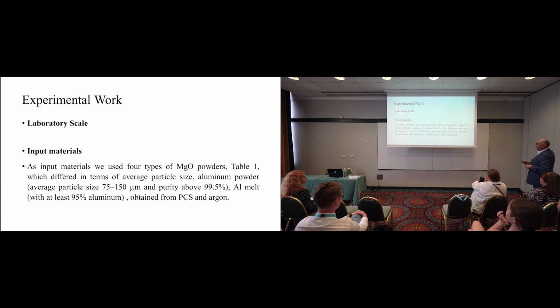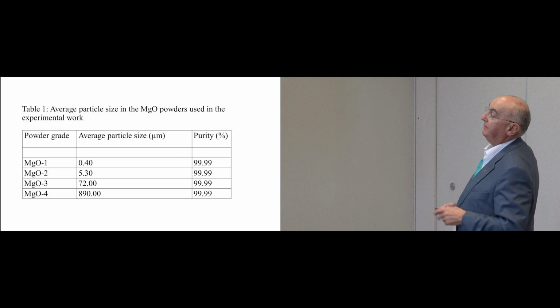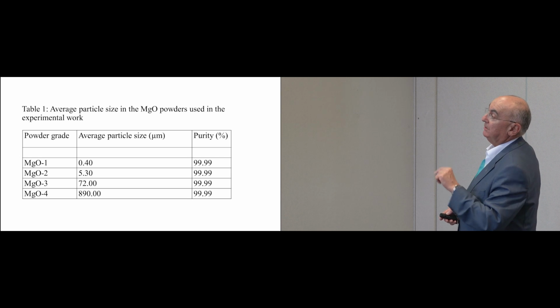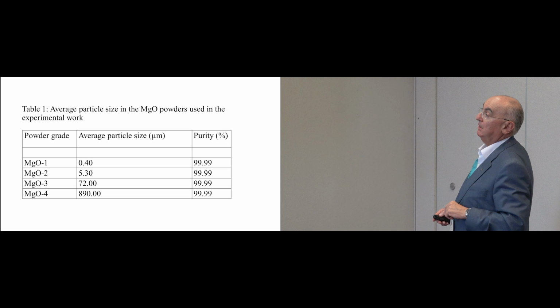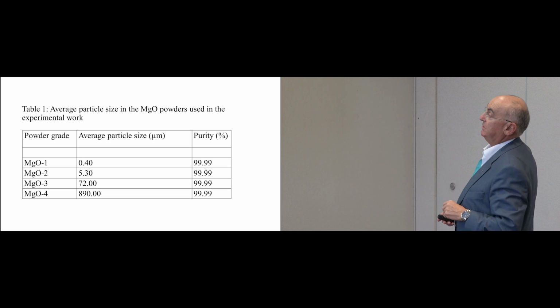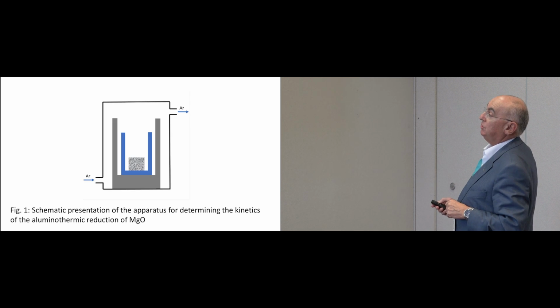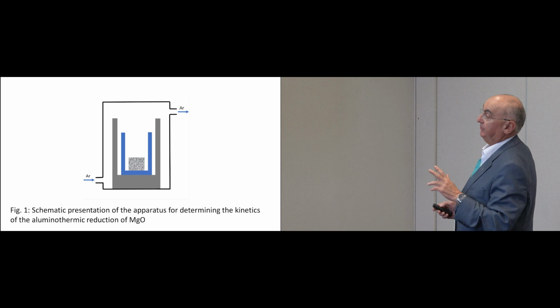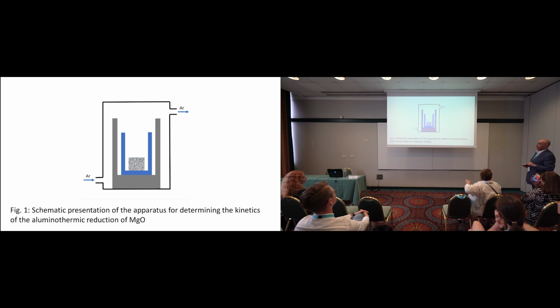So we used these commercial powders, of different average particle size. The first one was very fine with submicron particle size, and the last one was very coarse. Purity was very high. Then what we tried to do, in a pretty simple way, was to observe the kinetics of this reaction, but not to make kinetic studies, you know, it's too ambitious for us.